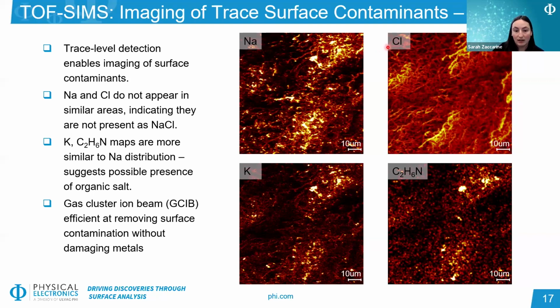If we compare this to the chlorine contamination, this tracks more consistently with the nanowire shape across the field of view, which suggests that this is more cohesive on the wires themselves. We also notice that the sodium and chlorine maps are not completely aligned, so they look slightly different, which means that this is probably not present as a sodium chloride. If we look at the bottom row of these potassium and amine contaminants, we see that this tracks even less so with that wire shape, and it's more clumpy and dispersed heterogeneously. So this suggests that these are likely more an external contamination and not necessarily something that is on the wires themselves.